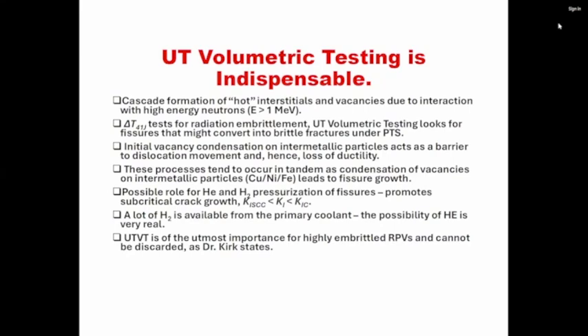These processes tend to occur in tandem, as condensation of vacancies on intermetallic particles leads to fissure growth. There is a possible role for helium and hydrogen pressurization of fissures, leading to subcritical crack growth. And lots of hydrogen is available in the coolant. Of course, they add hydrogen to the extent of 25 to 50 cubic centimeters per kilogram of H2O to the primary coolant. So there's lots of hydrogen around, but it's absolutely essential that ultrasonic testing, volumetric testing, be carried out, and it cannot be discarded, as Dr. Kirk states. That would be foolish. Next slide, please.